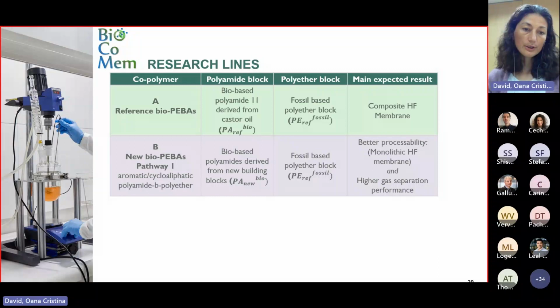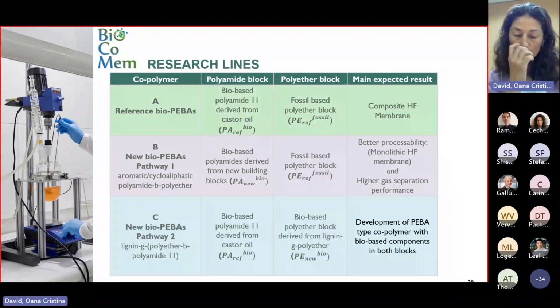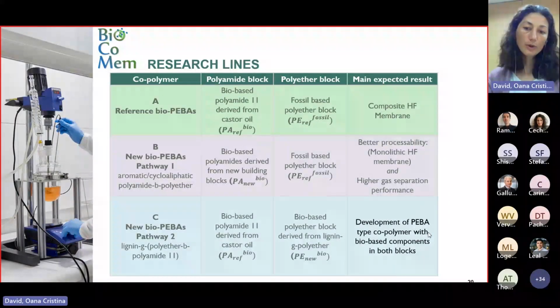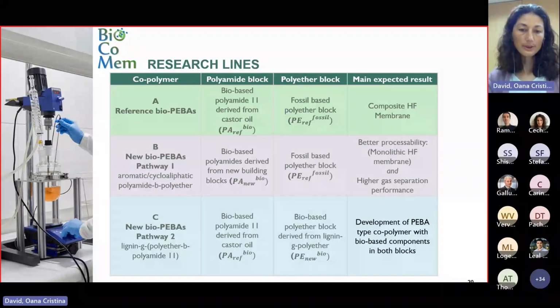And then in Tecnalia, we are working on prototype B. Here the chemistry of PEBA type polymers was tuned to be able to spin them as monolithic hollow fiber membranes. That was the main objective. So we kept the polyether constant for the moment, and we focus on changing the polyamide chemistry to be able to make spinnable polymers. And then we also had another research line where the main objective was to develop a complete biopolymer. And here we played with both blocks to have them bio-based. What I show here, polyamide 11 for the polyamide, was the starting point, but then in the project we also changed the polyamide part, and the polyether part, so all are bio-based in the final prototype C.